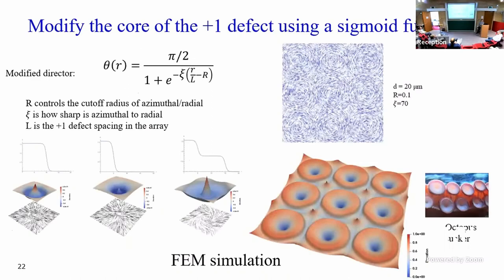Then Yusuf wanted to see if we could make something more interesting by not just doing pure radial or pure azimuthal, but by making a more complicated defect where it could be, for instance, radial at the core and azimuthal at the outside or vice versa. So just to give it some texture across. And it's characterized by two variables, one that describes the distance over which it changed, and the other one describes how rapidly it changes. And we got something that looked a little bit like octopus suckers.